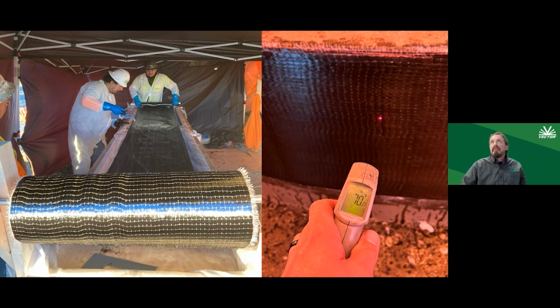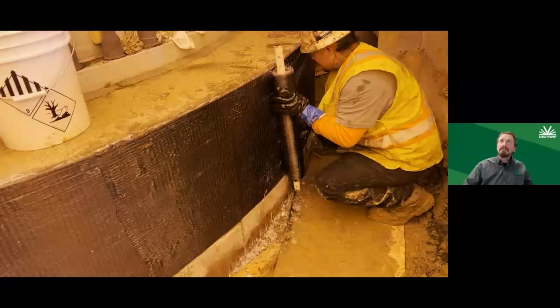In this case, the FRP was installed during the winter, so the containment was set up with heating so that we could bring the temperature of the concrete up to an acceptable heat, and then wrap everything, and then of course use that same heat to allow that FRP fabric to cure in place. It was a constant process, and then of course our layup table, we want to lay up as big of pieces as we can around the circumference of that foundation pedestal.